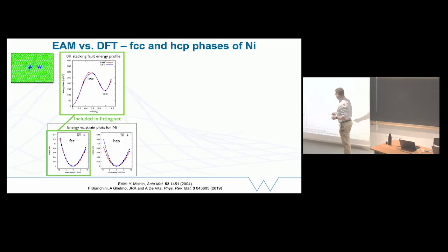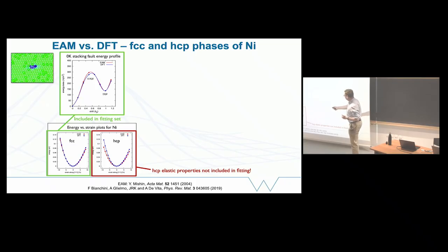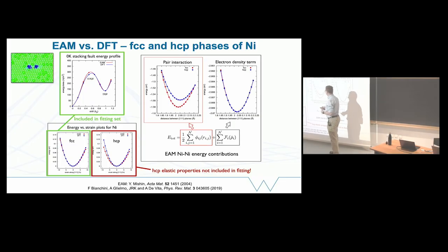This one, which is the HCP phase, the hexagonal close-packed phase, was not particularly thought to be important, so it wasn't included. Unfortunately, locally, if you look at the stacking fault, if you look at the atoms on the stacking fault, their local environment is much closer to HCP than it is to FCC. So this is an example of something you might not have thought of, but if you don't include it, you don't get this trade-off right, and you get a difference in the interaction, which you can't correct for in a simple embedded atom model where you only have a pair term in addition to the embedding term.